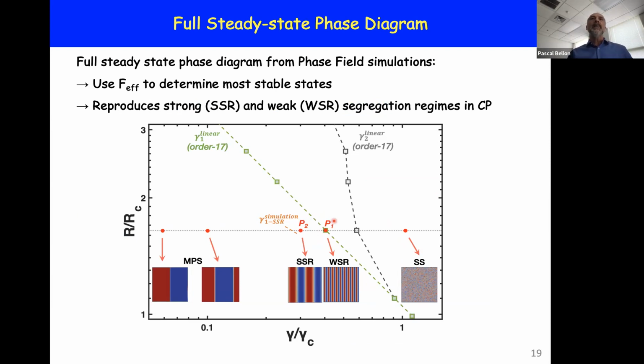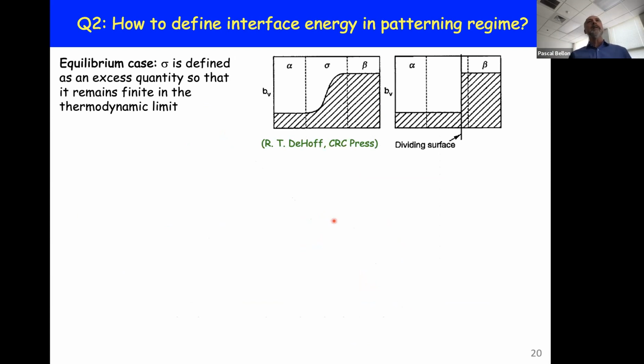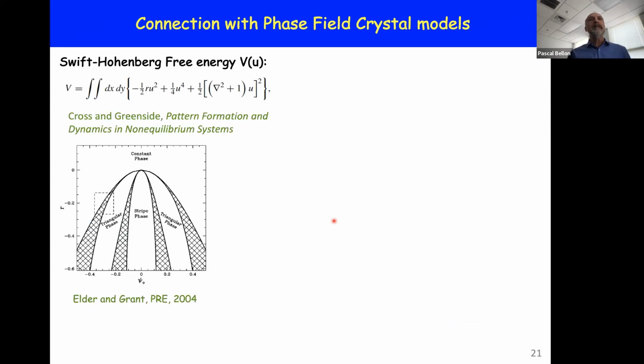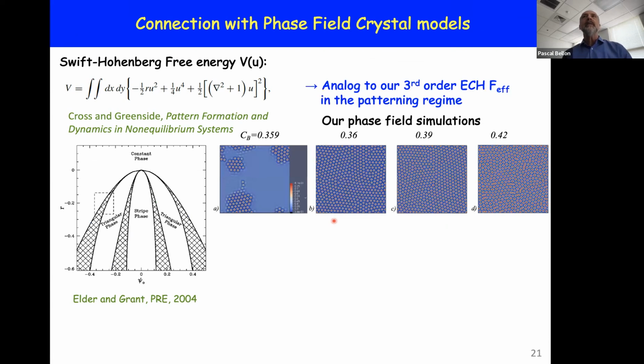This was in 2D for an equiatomic composition. Here, I think I'm going to skip this point in the interest of time. And so if one were to look at non-equiatomic compositions, in fact, this effective free energy that I presented before is a very similar form to the Swift-Hohenberg free energy that's been extensively used to capture pattern formation in non-equilibrium systems. And so, in some ways, our model provides a seamless description going from a Cahn-Hilliard free energy functional to this Swift-Hohenberg functional that's really heavily used for patterning systems.